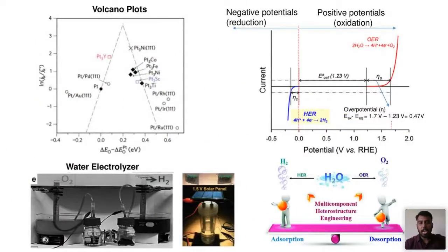The electrocatalytic activity can be determined from volcano plots. The metal with minimum adsorption energy performs well. For instance, platinum, nickel, and platinum yttrium have minimum energy and they perform well. And also the positive and negative potential, this is water splitting or bifunctional electrocatalysis, and the thermodynamic potential is 1.23. Whatever potential you apply higher than that is called overpotential, and in that way, by minimizing your overpotential, you can increase the production yield.